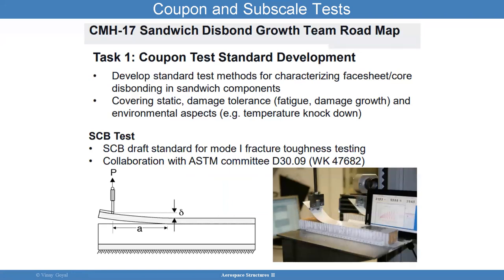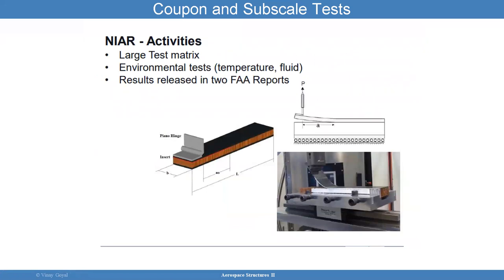There's also a whole team at CMH-17, the Composite Materials Handbook, looking at improving this particular test. It's basically a sandwich structure bonded at the bottom face sheet — you put in a flaw and pull the top face sheet out, with the goal of measuring the bond line face sheet-to-core interface fracture toughness. The National Institute of Aviation Research is also doing testing looking into that as well.